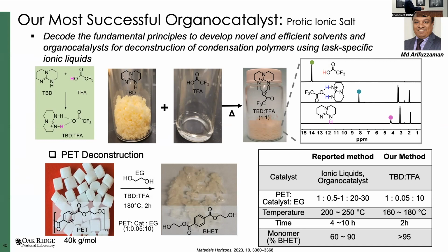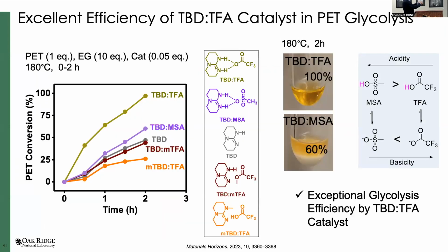There's a comparison in a little bit more detail. So this is our catalyst. This is TBD MSA, which was known to be the best before our publications. TBD is also this one. And we are also fundamentally looking at the importance of this hydrogen here. This methylated one is not as good. But showing here in the picture, after 2 hours, nice and clear. If using this, I guess the best material before our publications was still 60% conversion. So this catalyst is very effective with all the same conditions we use.